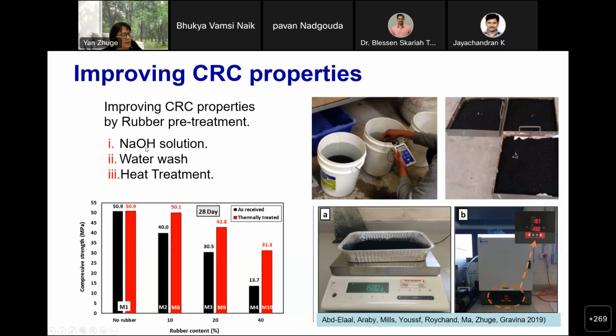We tried a NaOH solution, and the results indicate it's not a good option, because NaOH is not cheap, and after using the NaOH solution to wash the crumb rubber, the results were not really good. There was not much improvement at all. We also tried a water wash, and the results were even better than the NaOH solution, and it's cheap. You just need to wash it and get good results. So this method is kind of recommended.